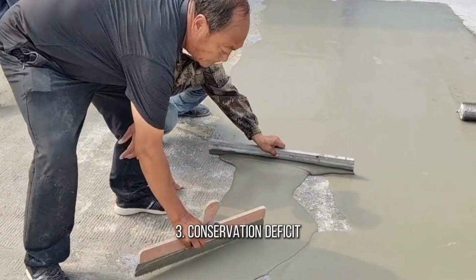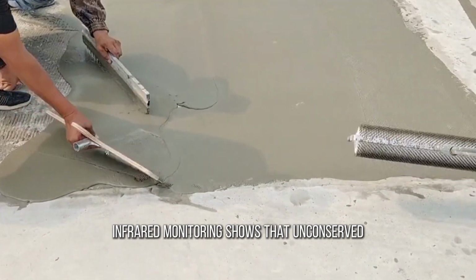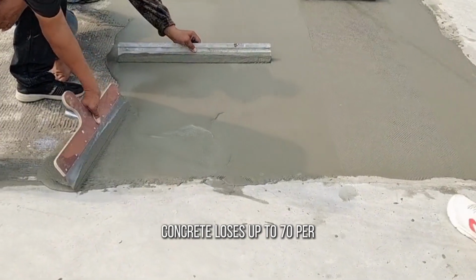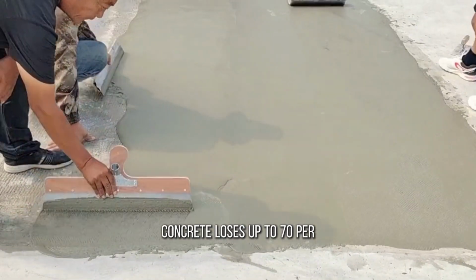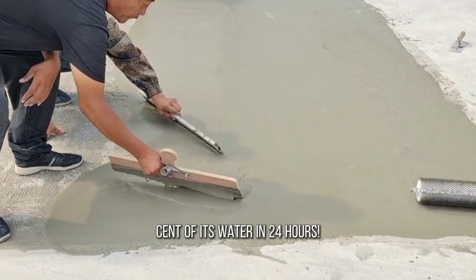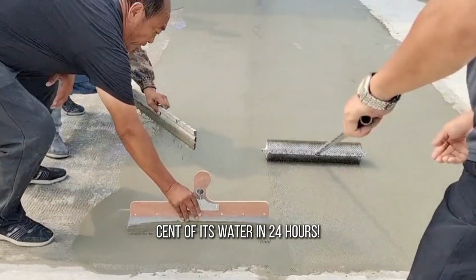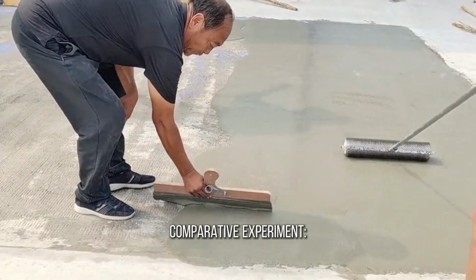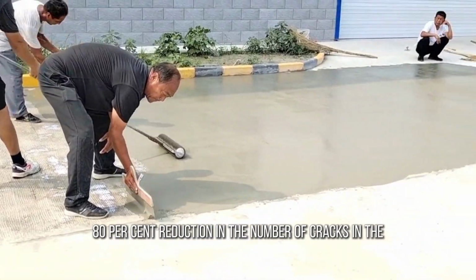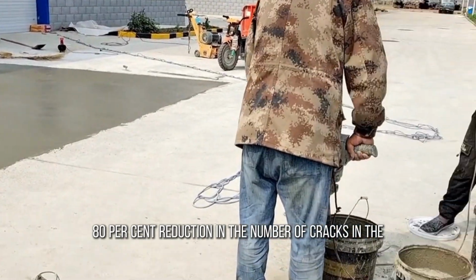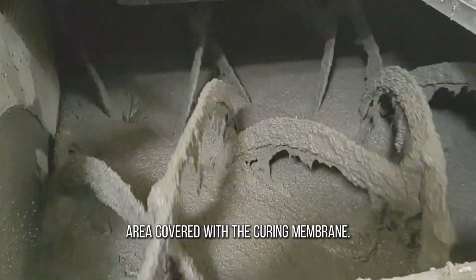Three, curing deficit. Infrared monitoring shows that uncured concrete loses up to 70% of its water in 24 hours. Comparative experiment: 80% reduction in the number of cracks in the area covered with the curing membrane.